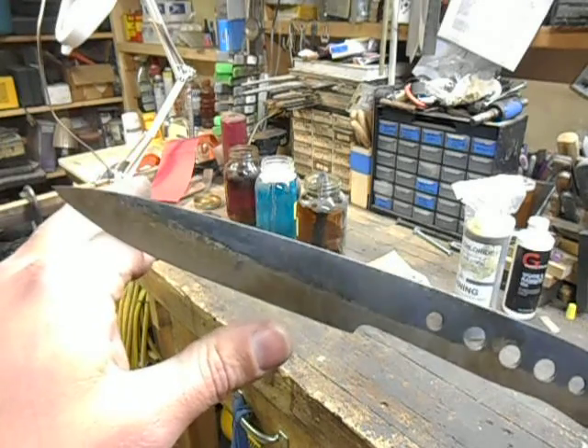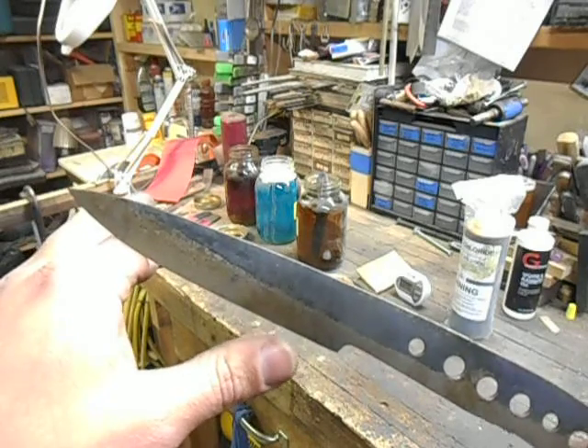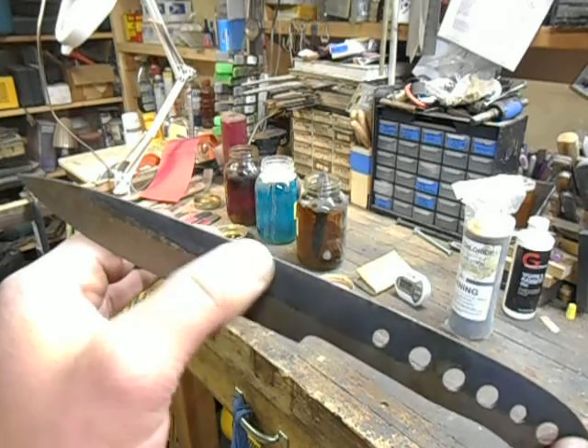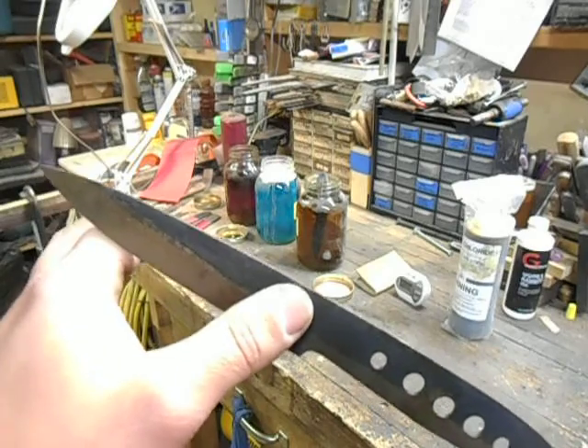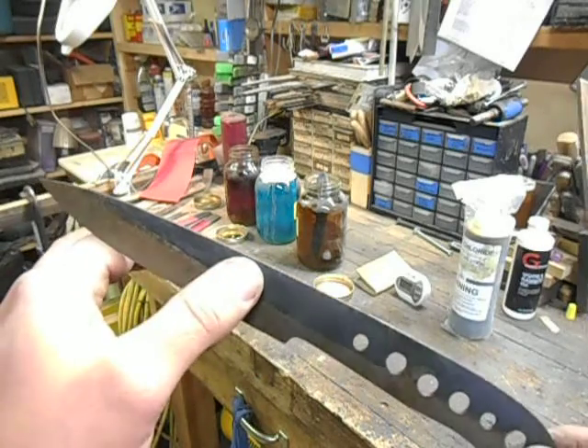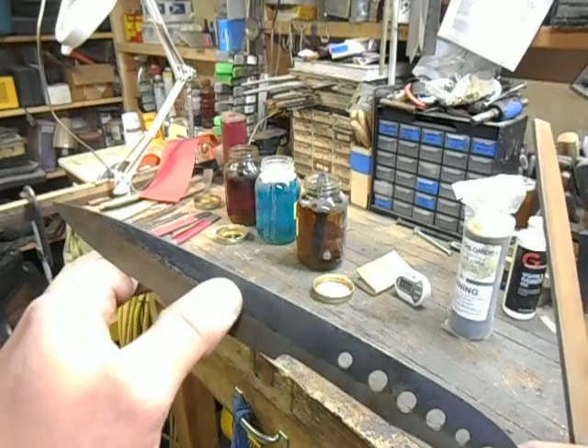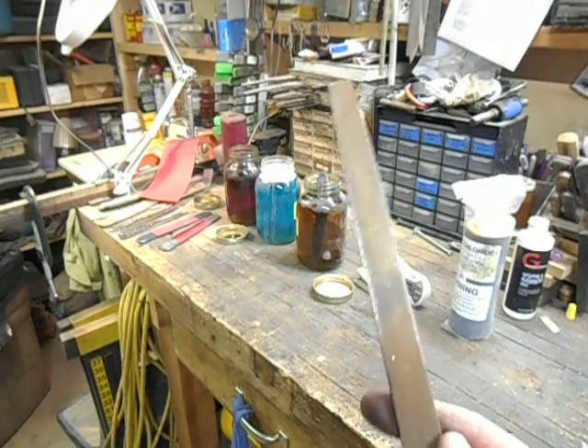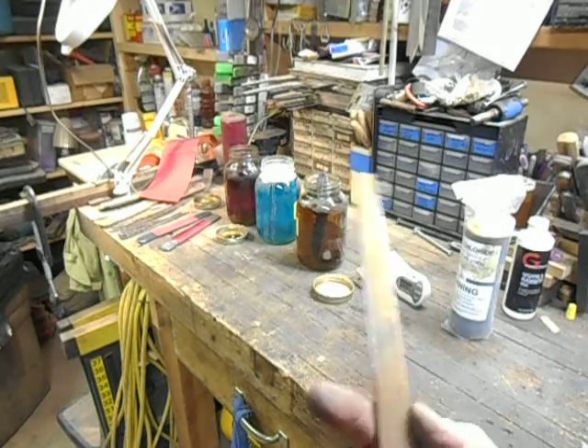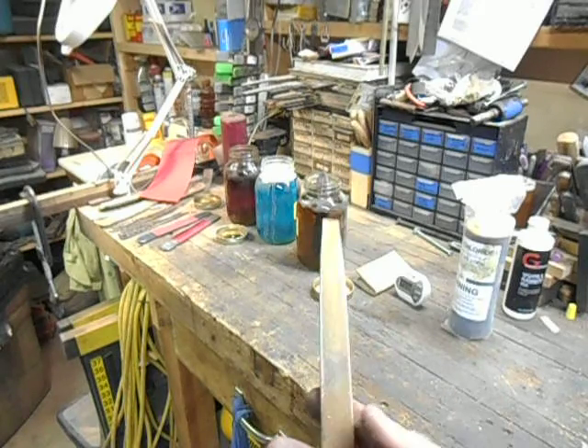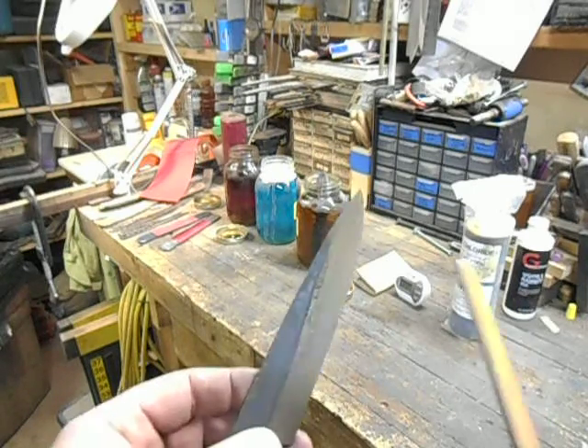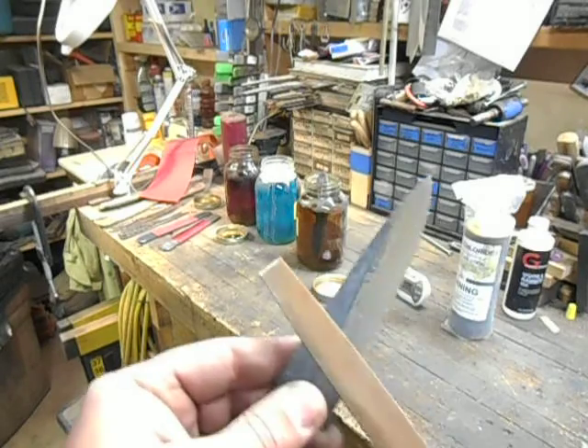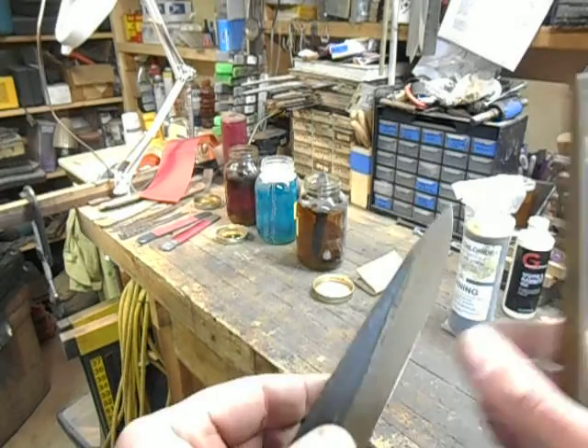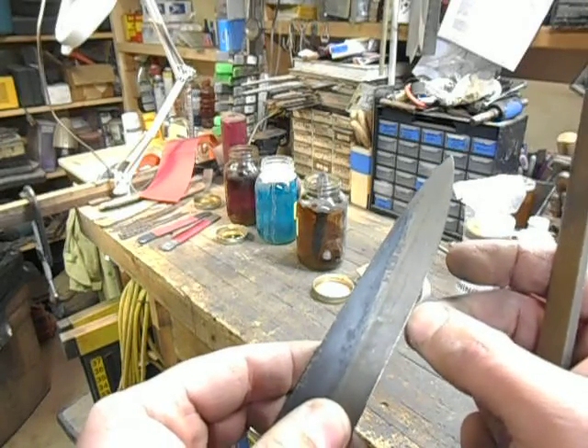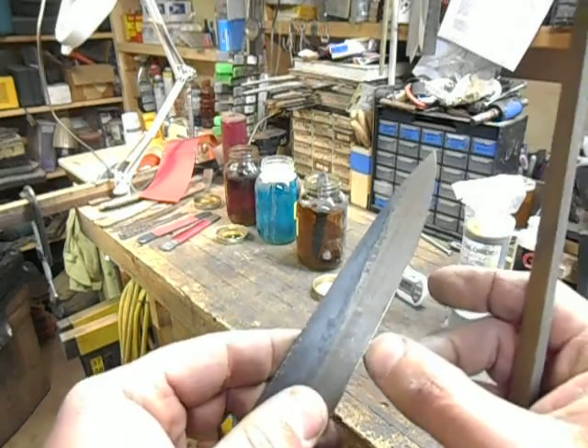Now 1095 also air hardens to a certain degree. Okay, so this black part, while it is unhardened, it just wasn't hardened in oil. It will still get some air hardening going on. So you can check with a file. This is a 8-inch Nicholson Black Diamond Mill Bastard file. So we can check it along the edge, and that sound you hear is pretty much, there'll be a layer of steel on the top that